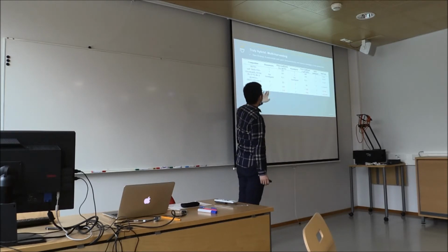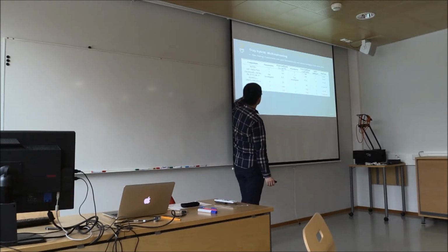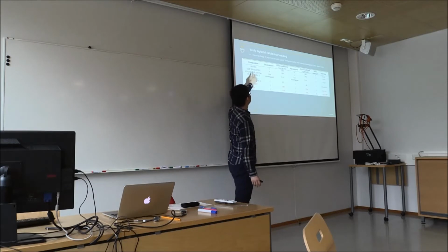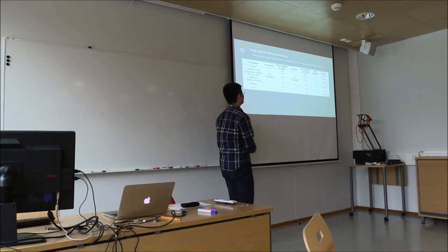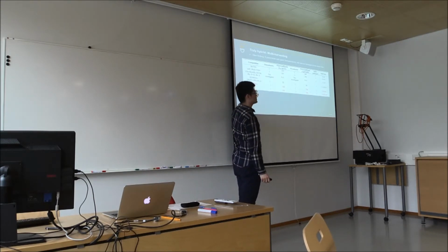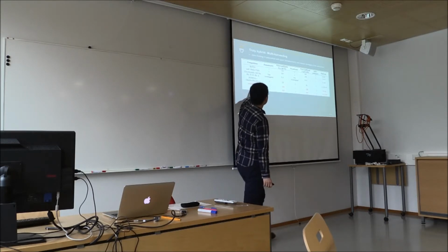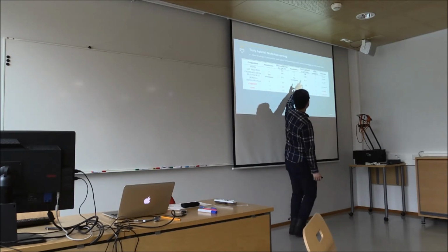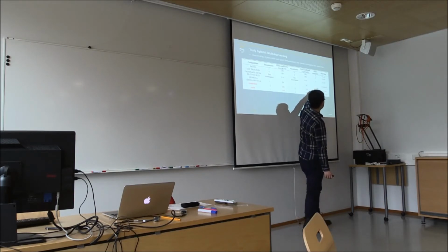But if we compare the individual properties, we can see this is pure KNN. By the way, we need KNN because we don't want the lead in PZT. This is a large research area in the world. Anyway, KNN can be the next piezoelectric material to be practically used instead of PZT, so I just compare with it. This is my material, this is pure KNN. We can see the piezoelectric coefficient is very similar, the pyroelectric coefficient is very similar, and the band gap is very promising for the new material.